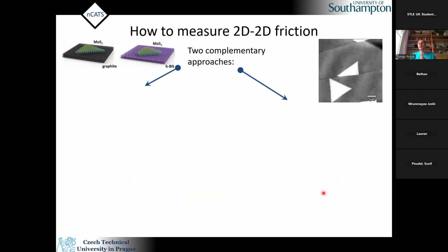So first, we needed to figure out how to measure the friction of 2D materials, because it's not so easy as you can imagine. This is something which is one layer of atoms like graphene, or three layers of atoms like molybdenum disulfide. How can we really measure it? So we developed a completely new method.